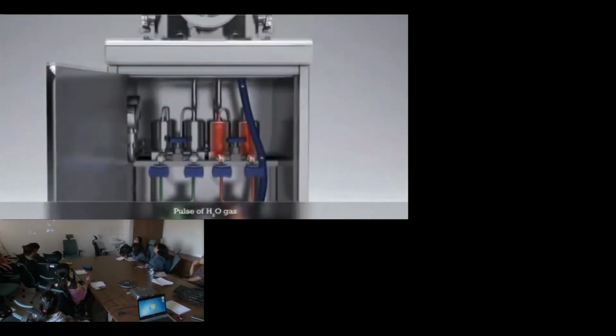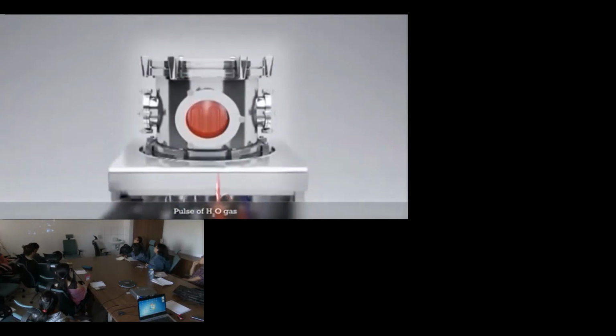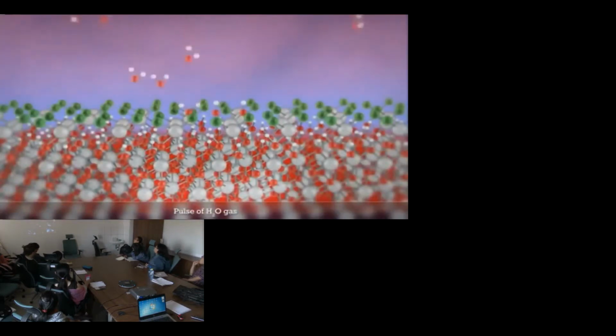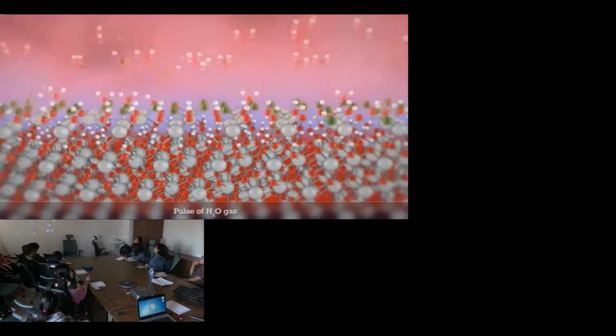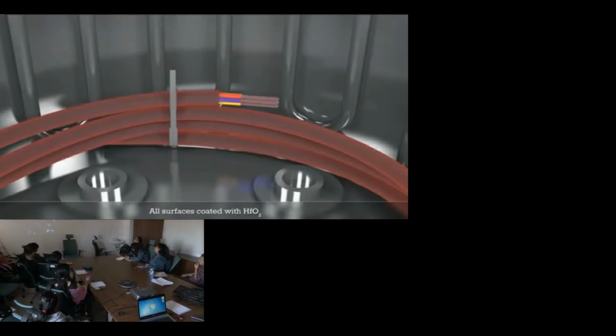So you see that the surface was saturated with a complete layer of hafnium chloride, and now a pulse of water comes, and the water reacts with this hafnium chloride, forming hafnium oxide. Yeah, so after this pulse, you can see that you have just a single atomic layer of hafnium oxide. And by repeating this process, again hafnium chloride, water, you can grow just layer by layer ultra-thin films of hafnium oxide. And now you see we are going again out of the fiber optic cable.